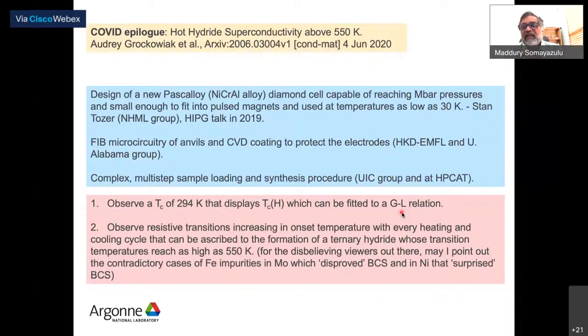But I think the bigger issue which came out of this measurement, and that is part of the reason why it is sitting on arXiv, is that people have a lot of time. There are a lot of disbelieving people out there. We were able to see, or Stan and Audrey, for example, were able to see transition temperatures as high as 550 Kelvin.